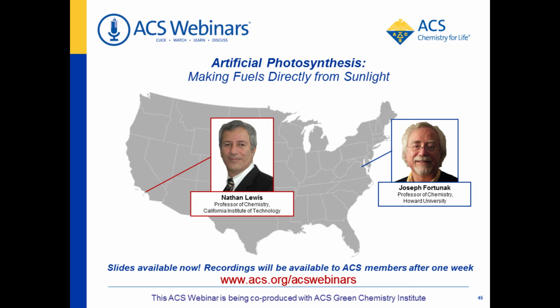In basic media, we've stabilized the materials that passivate and believe we have a strategy that will let us get good long-term stability on materials that actively corrode. And so we have got a lot of materials like gallium arsenide phosphide now and the 2,6 group materials for the anodes. That missing cathode, in basic media, we're looking at layered materials like tungsten diselenide and molybdenum sulfide and other 2D materials to serve as the cathode because they're not etchable in base, unlike silicon. And so that would be our preferred combination. And we already have membranes that are pretty good for hydroxide conduction. So those are the cards we would bring to that table to put an entire system together successfully.